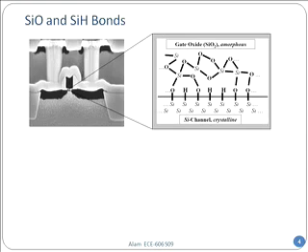This is that forming gas anneal. Remember that silicon dioxide cannot really satisfy all the bonds of silicon. Therefore, you need to tie up the extra bonds with hydrogen. Hydrogen has one proton, this has one dangling bond. So they make a covalent bond and everybody is happy.